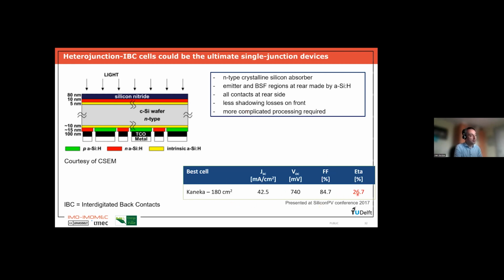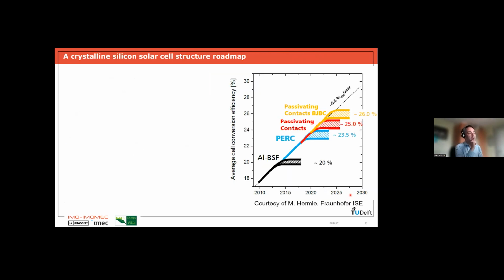The best cell achieved here is again in the same ballpark range of 26.7%, but this was already achieved actually 6 years ago by the Japanese company Kaneka. And in principle, we have here the potential of even going above 27%. So it's just a question of time before somebody reaches a higher efficiency with this type of cell. So this brings us then again to this roadmap. So we think that in mass production with passivating contacts at the rear of the device, so in a back contact device, we should be able in industry to produce on average 26% cells. Of course, not yet today. It still needs some time in the future, but this should be possible.